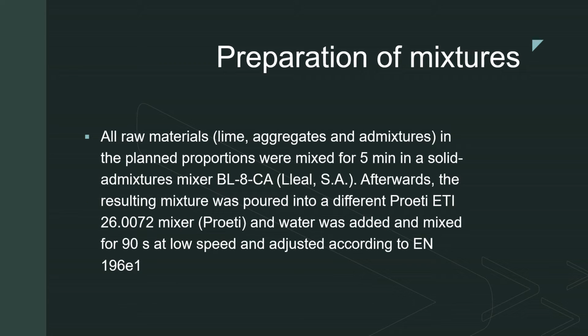Preparation of mixtures. All raw materials, limes, aggregates, and admixtures in the proper proportions were mixed for 5 minutes as a solid mixture. Afterwards, the resulting mixture was poured into a mixer, and water was added and mixed for 90 seconds at low speed and adjusted according to EN 196-1.